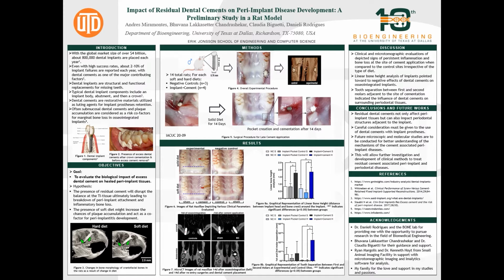Dental cements are luting agents that are used for implant prosthesis retention, though there is a lack of preclinical studies evaluating dental cements as a primary cause for the development of peri-implant diseases, as realistically, up to 50 times the ideal amount of cement required can be placed. This practice has led to residual cement accumulating in the operating area, which may act as a cofactor for development of peri-implant disease. The aim for this project is to evaluate the biological impact of excess dental cement on healed peri-implant tissues.